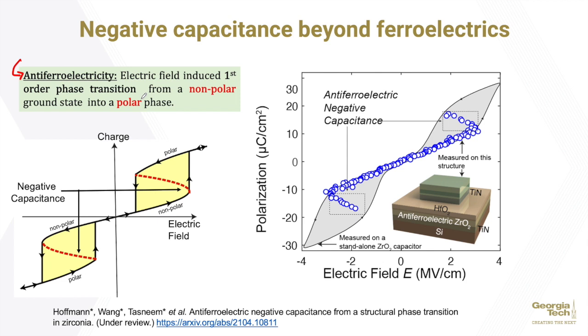So we took an antiferroelectric zirconia, and using the pulsed capacitance method, we could see that we have a similar kind of negative capacitance in this antiferroelectric material that one can obtain in a ferroelectric material as well. So altogether, it suggests that negative capacitance might be a general phenomenon across many different material systems beyond ferroelectrics that exhibit phase transitions.